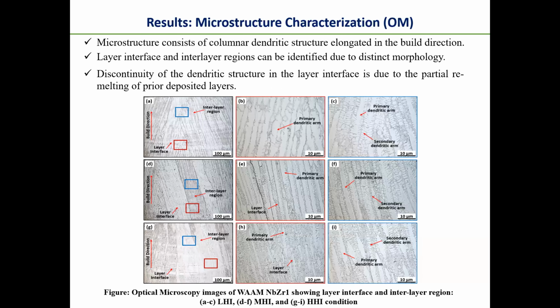So after that, we did the microstructural characterization. First, we did optical microscopy to see the microstructure. The microstructure mainly consists of columnar dendritic structures, which are elongated towards the build direction. This is very common in AM components, and we could not find any cracks or porosity in our structure. Layer interface and interlayer regions could be easily identified in the OM images, which are shown at higher magnification in the blue and red regions. In the layer interface, there is discontinuity in the dendritic structure. This is maybe due to the partial remelting of the deposited layers.